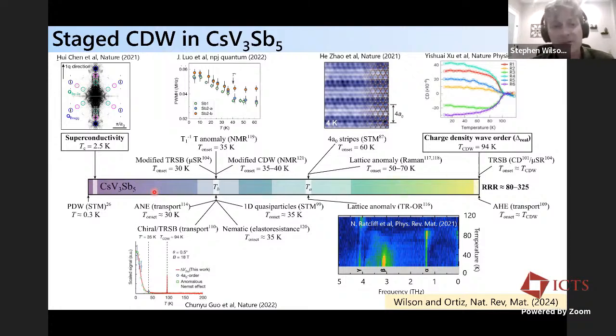And then as you cool the system toward the superconducting phase, it also shows this very complicated and rich hierarchy of energy scales as you cool the system, okay? I can't go through them all, but suffice to say there's one energy scale, say around 60 Kelvin or so, where, for instance, you see the onset of short lifetime lattice modes in transient optical reflectivity measurements and Raman measurements. You also see the onset of quasi-one-dimensional stripes on the surface of the system.